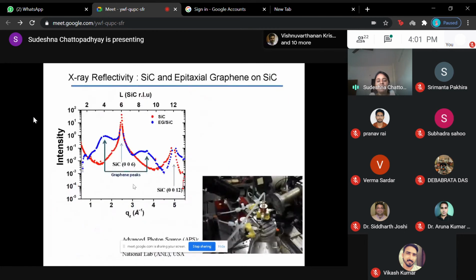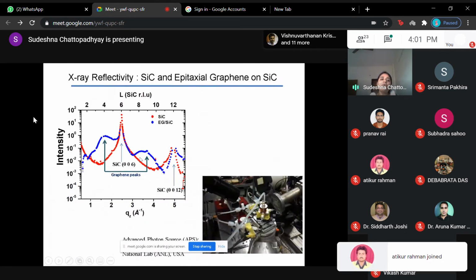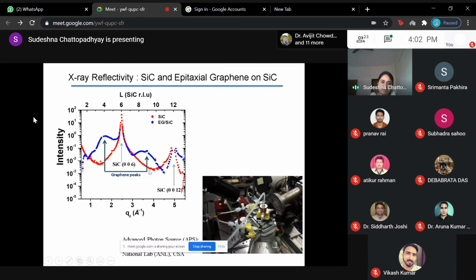So here I wanted to show one example of how we can get the features for the silicon carbide as well as the graphitized silicon carbide. Here, epitaxial graphene on silicon carbide, I have given the name EG/SiC. Okay, so these two peaks, as I have told, are the silicon carbide hexagonal 006 plane, because it is epitaxial around this direction. The second order peak is at 0012, and now you are just getting this hump when there is only a single layer of graphene. Can you imagine? So this hump is coming, and with any other technique it is very difficult.